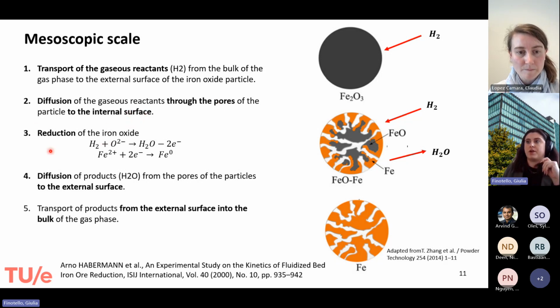Then at the surface you have the reduction of the iron oxide, and with that you see the formation, on the outside layer, of iron, while inside you still have, in this case, wüstite. And then the product, which is, of course, water vapor, needs to diffuse back from the pore to the external surface. And then you have the last step, which is the transport of the product from the external surface to the bulk again. And where you end up is, again, what I showed before, a very porous structure of an iron particle.